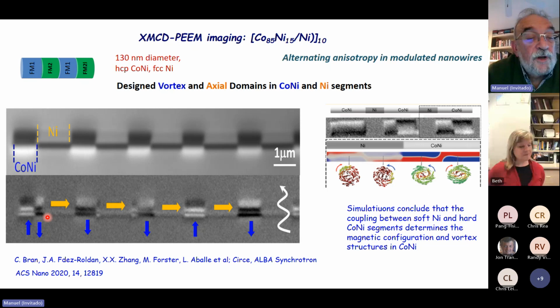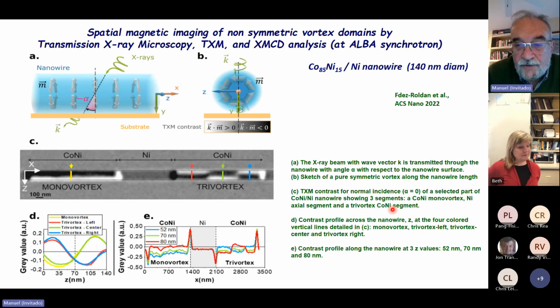And at the bottom, we have magnetic force and PEEM images, where we have the cobalt nickel, which is hexagonal. We have two vortices with opposite chiralities here. The nickel segment magnetization is axial. In the cobalt nickel, we have vortices, and in the nickel, we have only axial domains. Well, we have been also doing some simulations. I would like to mention the very last experiment we have done also on this type of cobalt nickel multi-segmented nanowires with the transmission X-ray microscopy, also with circular dichroism analysis, which is interesting here, and has been recently published.